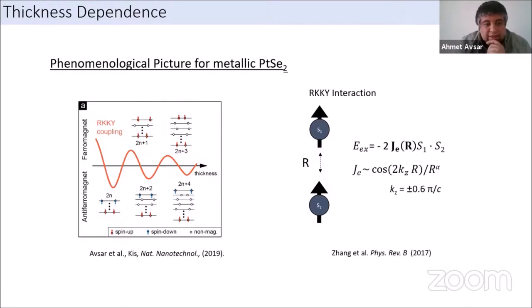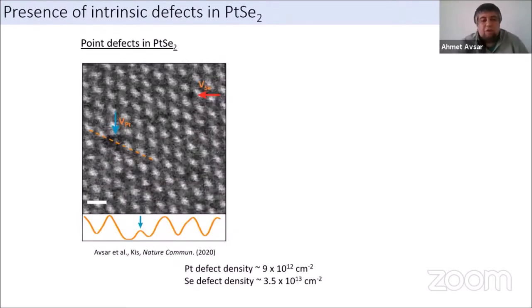So what it says is, as the thickness of the material is increasing, the strength of the magnetism is decreasing, okay? But more interestingly, it shows that if you change just one layer, you can change the type of the magnetic ordering from ferromagnet to antiferromagnet. So adding or removing one layer is sufficient to change the magnetic ordering in this material. And the question was, do we have this kind of defects in these materials?